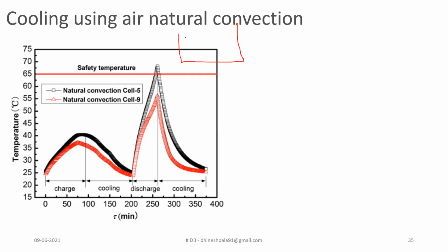Here the batteries are placed at a minimal distance between each cell, and the air acts as the medium for cooling. In that case, they charge the battery for the initial 100 minutes and allow it to cool for the next 100 minutes. As I described earlier, at the time of charging you will have a drastic temperature rise, and after that, at the time of cooling, when it is kept idle, there would be a drop in temperature. After that, they discharge the battery in the next 50 minutes.